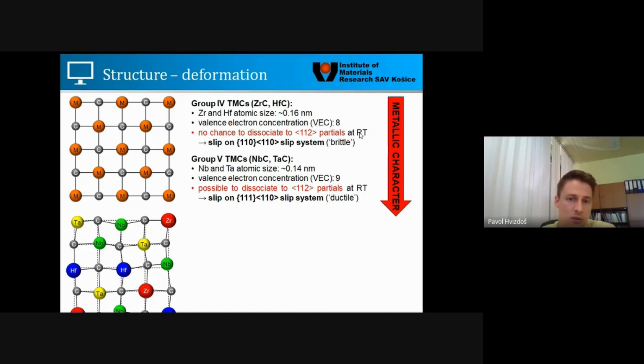This is predicted by DFT calculations. And this is the reason why they slip only on the 110 planes, which is the so-called brittle plane. Of course, if we increase the temperature to about 800 degrees C or even more, there is a chance of a brittle to ductile transition, but we were interested only in room temperature because this is the problem usually when we have brittle materials.